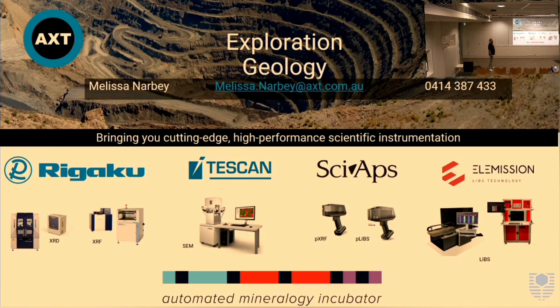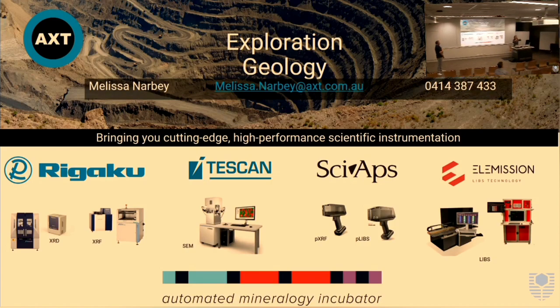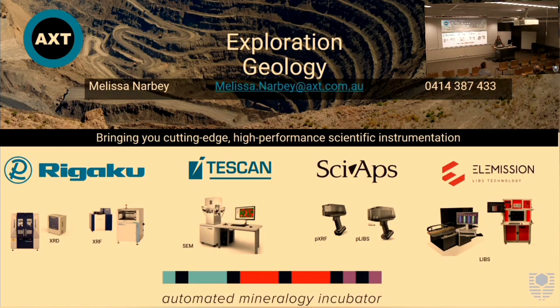Yeah, because it uses mineral chemistry. Could the laser impact itself change the mineralogy, the heat of the...? No, not that we've seen. And does it sputter? Yeah, it forms a crater a bit like a volcano, and that limits how far apart you... So we've found that if you do one zap, there's a vacuum that sucks up the dust. If you don't have that vacuum, you get dust everywhere, but it's a heap of vacuum right next to where it's being ablated, so it stops that from happening. But if you do one zap on the one spot repeatedly, you see a volcano crater around it, so in that case that would limit your spacing between points.